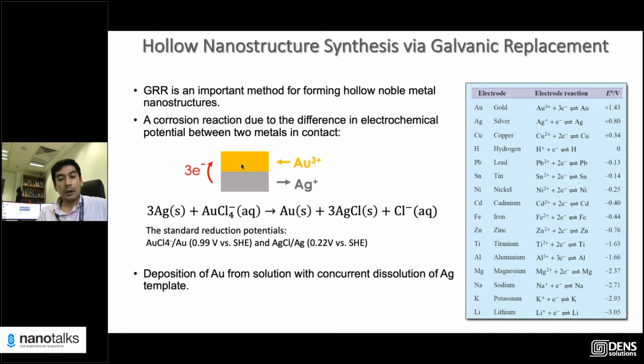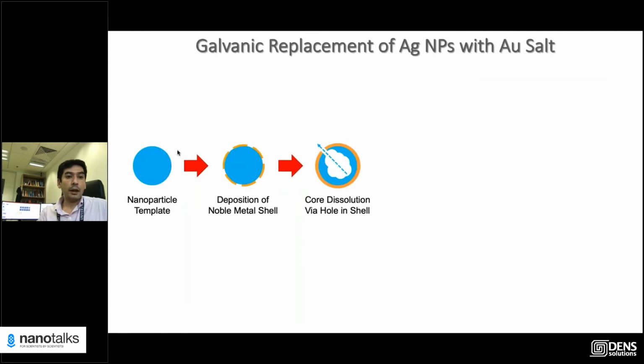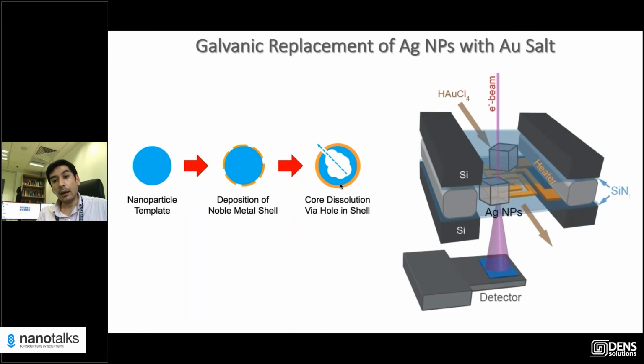How this etching happens is described in the basic schematic here. You have a template material, and you're depositing, in this case, gold from a gold chloride solution. You will have pinholes through which the reaction can occur, and the gold can go inside and slowly corrode it away, and you end up with a hollow nanoparticle. And again, this can be looked at by using the in situ liquid cell, and that's exactly what we did.